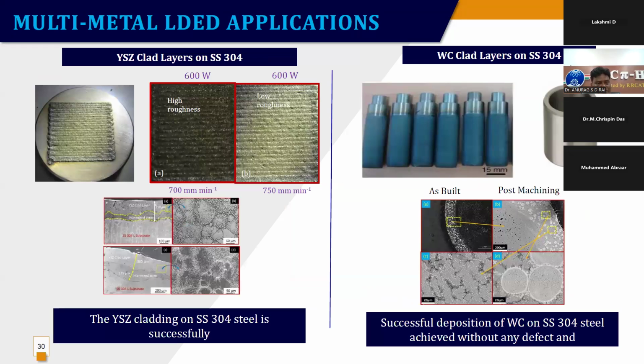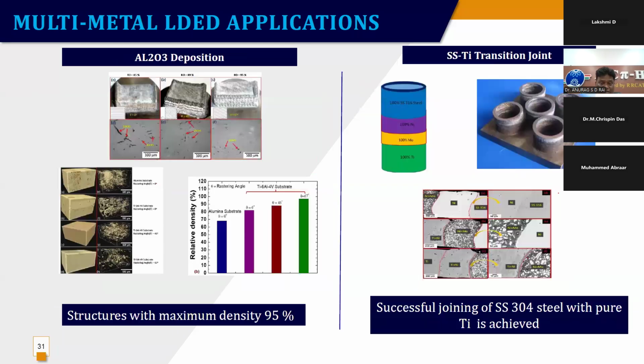There was also a requirement to deposit yttria stabilized zirconia on SS304. Successfully it is deposited for some of the applications that we have in our industry. And for one of the applications, they wanted tungsten carbide deposited on SS304 without any defect. So again, we did, and this application is really very challenging, and things are really changing the scenario here, just to show that tungsten carbide can also be deposited. Alumina is deposited on SS. The things were tried out. We could achieve 95% density.